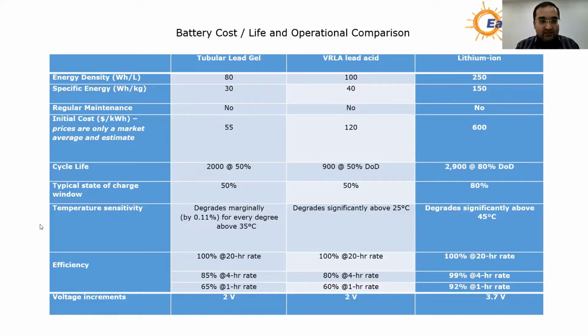So as I said, the temperature sensitivity. Due to the advanced polymers used in the tubular gel battery, the capacity degradation that happens in the battery is reduced to a great extent, by almost 80%. So for every degree that goes above 35 degrees centigrade, the capacity will degrade only by 0.11% in the tubular gel, while in the VRLA lead acid, it degrades significantly, over 3 to 4%. And in lithium-ion, it nearly goes down by 50 or 60% if the temperature is above 45 degrees centigrade.